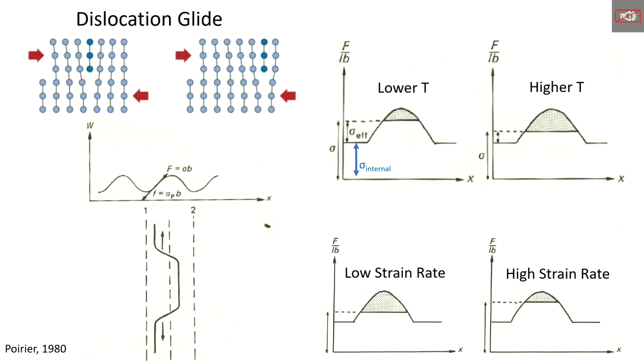But there's a little bit of a weird thing in here. There's this extra bit, the internal stress. When you put that defect into the crystal, it distorts the lattice in a way that's applying a stress against what you're trying to apply in the first place. So before anything happens, to just get to zero, really, in terms of the dislocation, you have to apply a stress. Then you have to apply even more to get it to move. Some of you might have heard of people like Lars Hansen talking about backstress and its application for understanding attenuation of seismic waves. That internal stress is the origin of that.